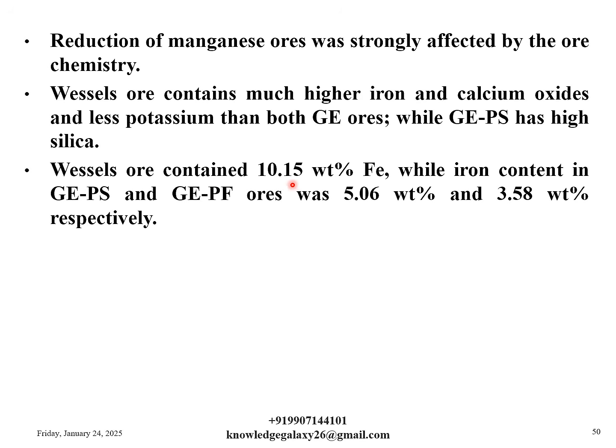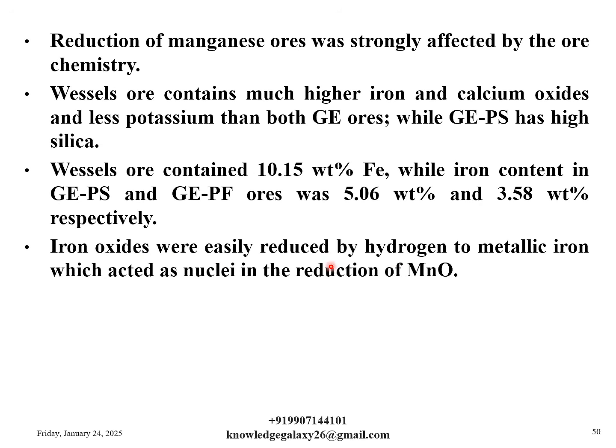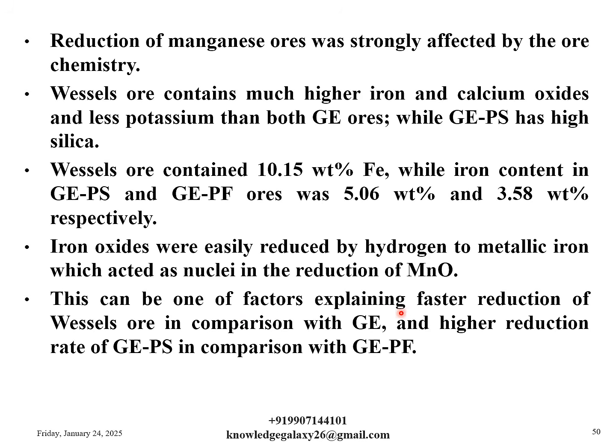Wessels ore contains 10.15 weight% iron, while iron content in GEPS and GEPF ore was 5.06 weight% and 3.58 weight% respectively. Iron oxides were easily reduced by hydrogen to metallic iron, which acted as a catalyst in the reduction of MnO. This can be one of the factors explaining faster reduction of Wessels ore in comparison with GE and higher reduction rate of GEPS ores in comparison with GEPF.